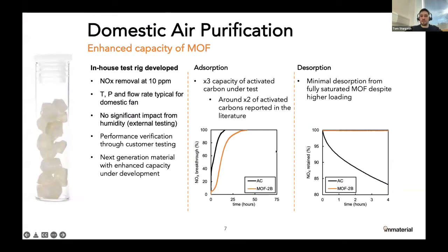So to share some of our experimental data now, as I said, this is for our material MOF2. So this is the kind of controlled laboratory testing that Nick was talking about earlier, which certainly doesn't give a full picture, but is our initial go-to to start to understand the performance of different materials. So in our test rig setup here, we've introduced NO2 at 10 ppm. And then on the back end of the filter bed, we've got a total NOx detector, and the temperatures, pressures, and flow rates that we're using are typical for a domestic type of fan.